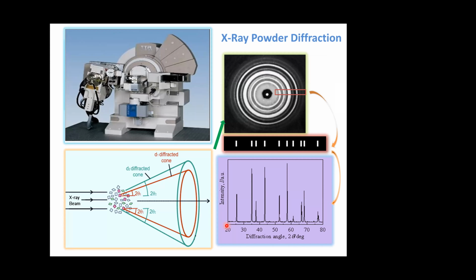If you get powder, then in a lot of labs these days, everyone has what we call X-ray powder diffraction. It's very simple. You put the powder sample on the machine, and with the X-ray, instead of a three-dimensional diffraction pattern, you get this so-called diffraction profile right there. Each peak that shows up at a different 2 theta becomes the fingerprint of your material.